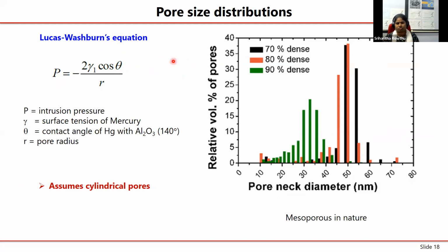Now in mercury intrusion porosimetry, what is happening is that the mercury has to be pushed through the pores of alumina. If you simply put mercury on the porous alumina, it is not going to enter the pore because of its very, very high surface tension. It would prefer to be simply a spherical drop. But the same porous aluminum oxide, if you place one drop of water on it, water will immediately go inside. But mercury is not going to go inside. So you have to apply a pressure, which is here P, called the intrusion pressure. And gamma here is the surface tension of mercury.